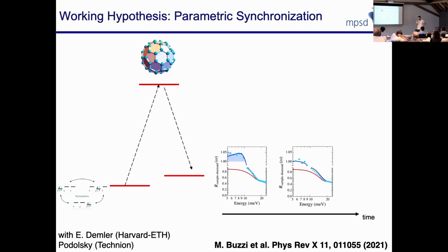The reason why we think this is the case is that if you look at the earliest time delays, before the system is set into this long-lived reflectivity equal 1 state, we consistently find an amplification of the probe pulse. So there seems to be some coherent parametric process where at early times you get more probe light than you put in. So there's clearly something that is non-thermally being pumped at the beginning, and we have various theories about this, but we're trying to substantiate this